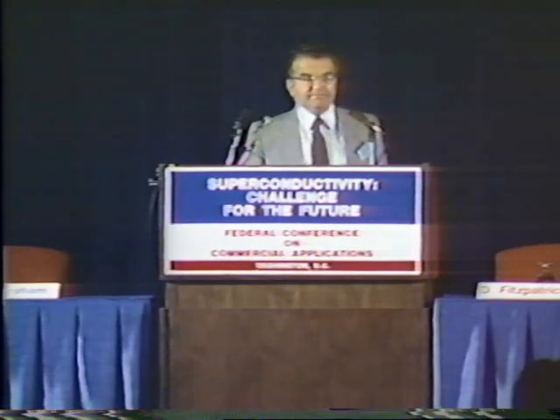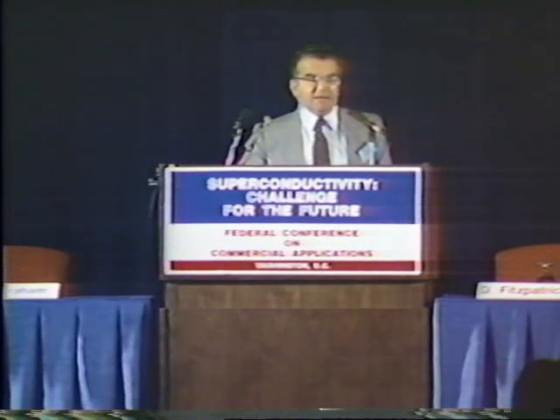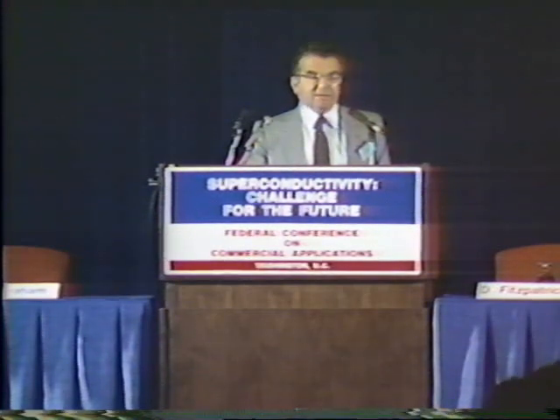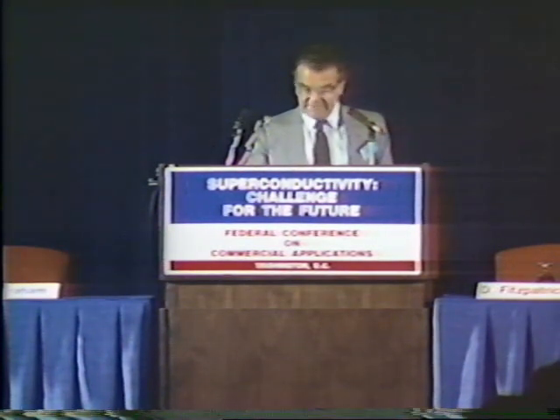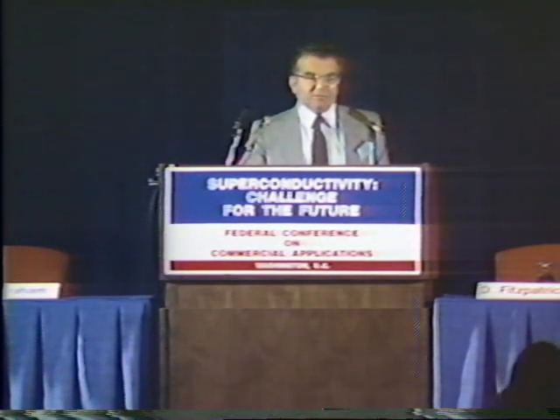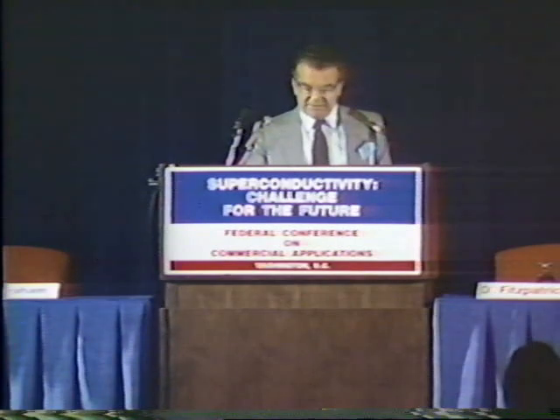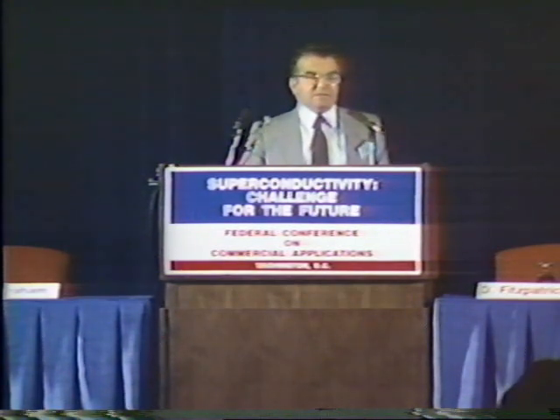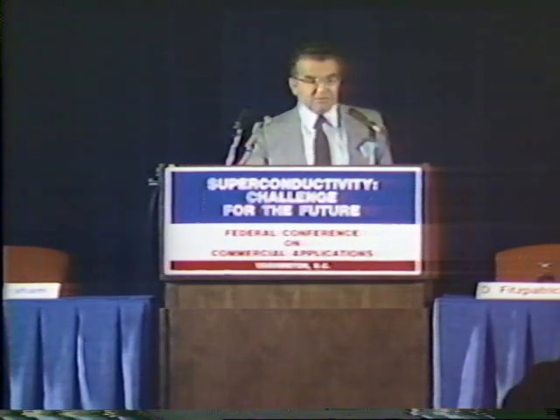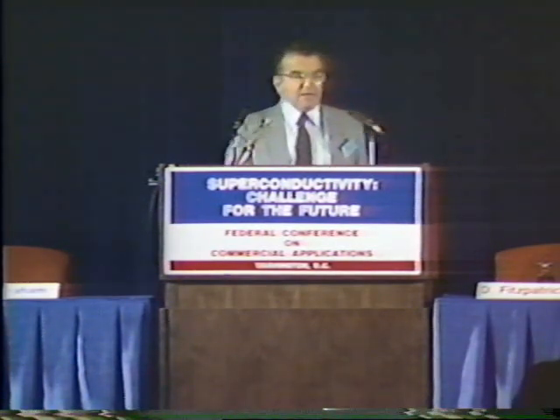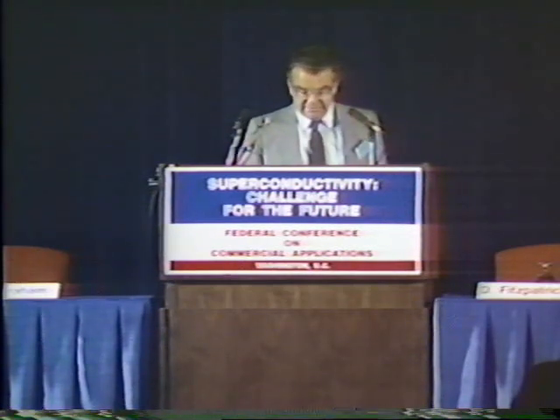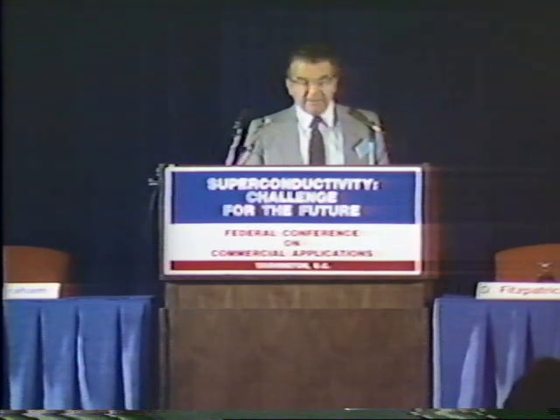Now that top film, as I've told you, has to be deposited and then heated to 900 degrees. So after you've made the bottom film and oxidized it in some way, you have to reheat the structure at 900 degrees centigrade. And that's something that we certainly never contemplated before with any of the earlier materials. And I suspect that in fact what we'll have to do is invent a new kind of device or a new way of making the Josephson junction that avoids that second film heating, some kind of internal deposition of the oxide layer. Now again, once we understand the physics of these materials, I think there will be new devices, and that's what I'm almost saying has to be invented in place of the Josephson tunnel junction.